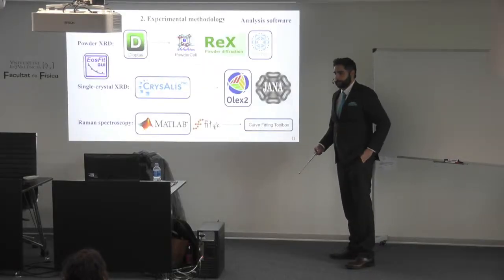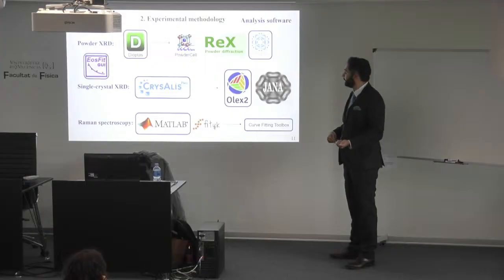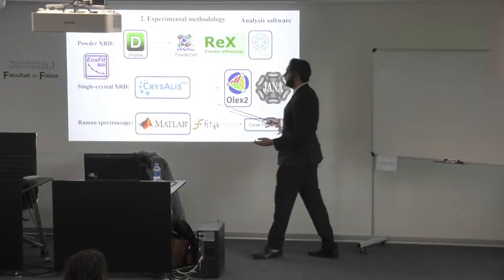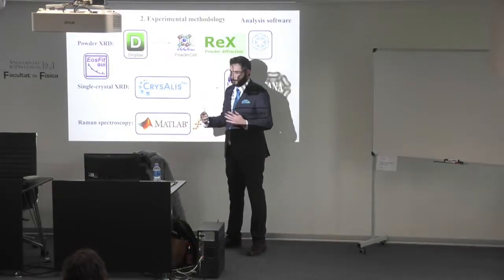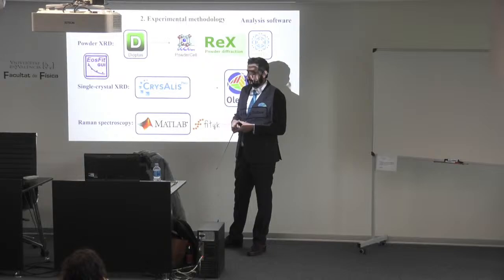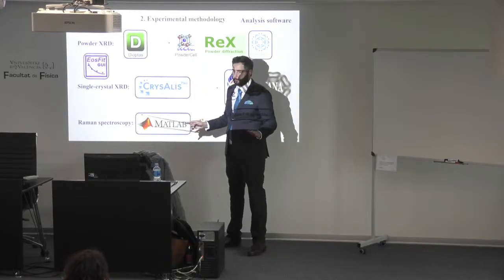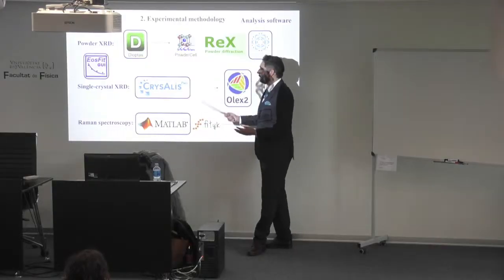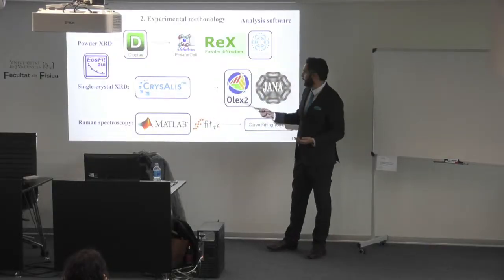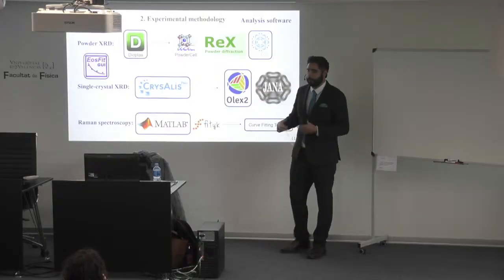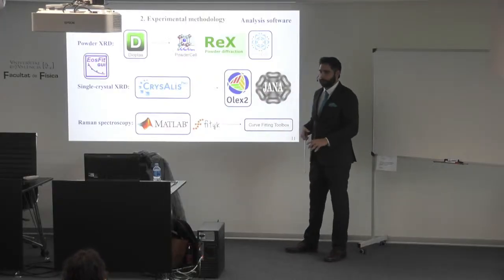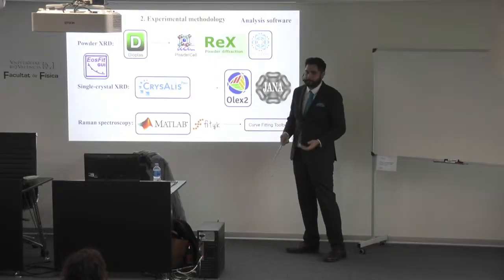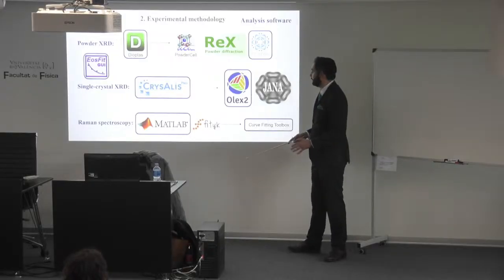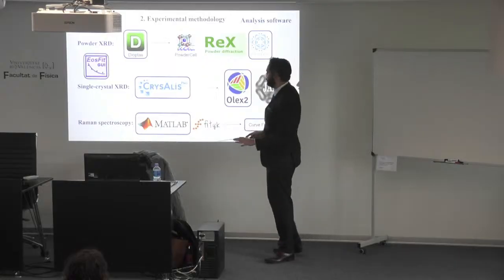After getting the information and the spectra, we have to analyze and process this information. When we have powder XRD, we always have to integrate the diffracted image into a spectrum. This is always done with Dioptas. And then we choose our software of preference. I used PowderCell and Rex at the beginning, and then I discovered Profex. So I switched to that, and this is the one that I reflect in the thesis, and the one that I recommend. But it's up to the experimentalist to choose.